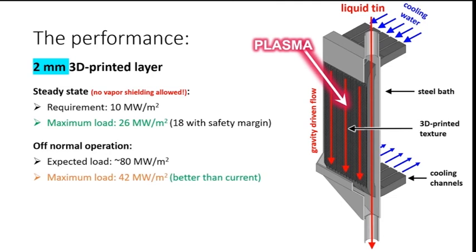In off-normal operation, so let's say we lose control of the plasma for a little bit, we could expect the heat load to go up significantly to about 80 megawatt per square meter. And this is still too much. I would predict we can dissipate around 40 megawatt per square meter. That is much better than the current state of the art, but still it's not enough.